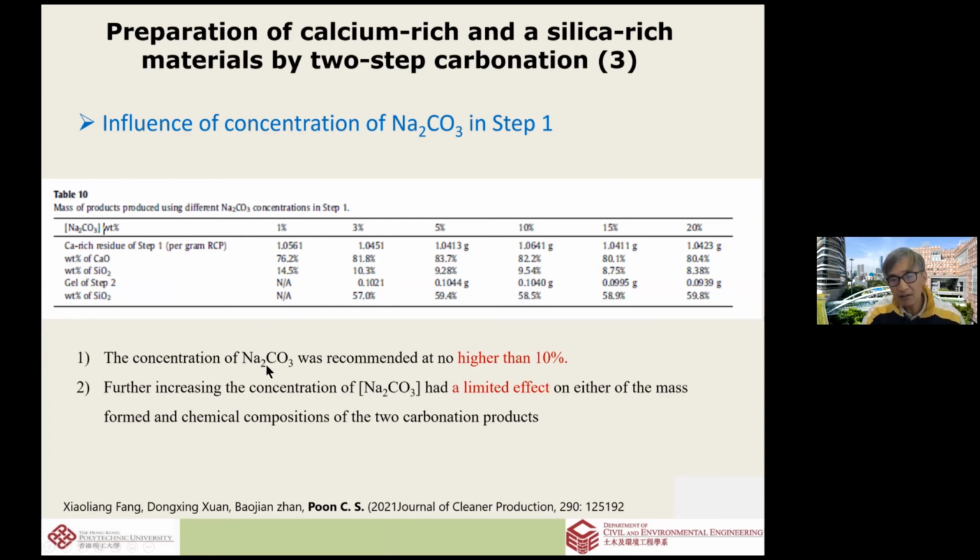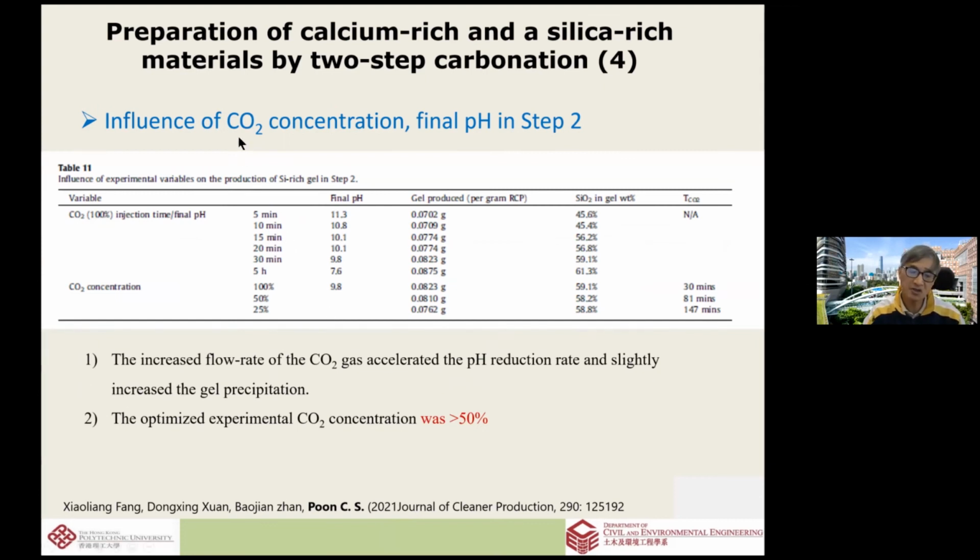So we found that the concentration of sodium carbonate does not need to be very high. And then how about the CO2 concentration? The CO2 concentration needs to be sufficient, but it does not need to be pure CO2.